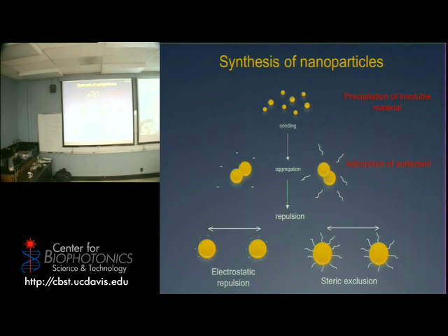If you take another common material like cadmium selenide, for example, you do the same thing. You start from a cadmium precursor, typically an organometallic complex, and you heat it up very hot, and you start decomposing. And if you're in the presence of a selenide source or a sulfide source, depending on the quantum dot you're trying to make, you form these seedlings.